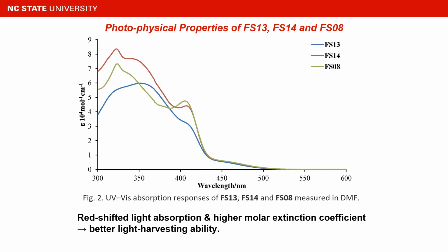This slide illustrates the photophysical properties of FS13, FS14, and FS8 by drawing the UV-visible absorption curves for our three compounds, which were measured in DMF. We found that the redshifted light absorption and the higher molar extinction coefficient lead to better light harvesting ability.